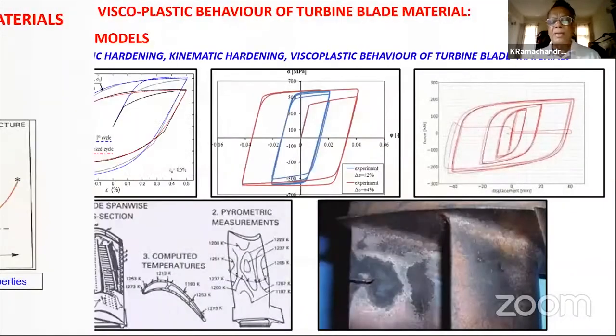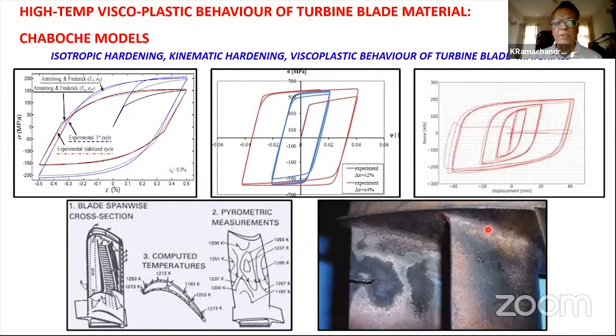But how to predict the creep-fatigue interaction at those temperatures, where the loads are cycled, where the stresses are cycled, we have quite different types of behavior. Some of them are isotropic hardening, kinematic hardening. I won't go into the details, but they basically behave as viscoplastic material. There's a viscoelastic plastic behavior, and all this needs to be integrated to be able to predict creep-fatigue interactive damage. And there are very many models available today, and we have to put them all in closely and be able to predict the onset of damage to the part, to a turbine blade or turbine vane.